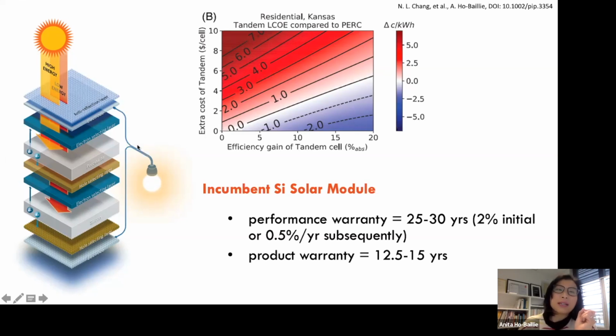What it assumes is the perovskite will last as long as the silicon. Now, the silicon solar module that you have on the roof has two warranties. One is a performance warranty of 25 to 30 years, meaning the first year you'll get a 2% degradation, and then in subsequent years 0.5% for say 25 years. Altogether you get around 12% or 14% degradation over the 25 years.